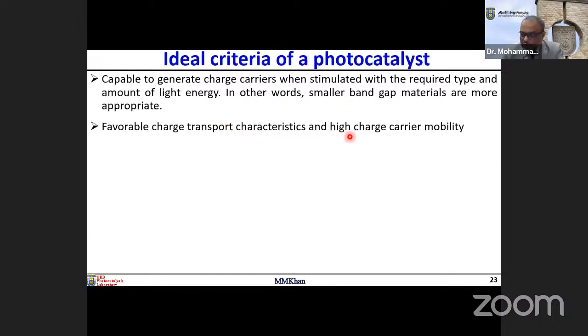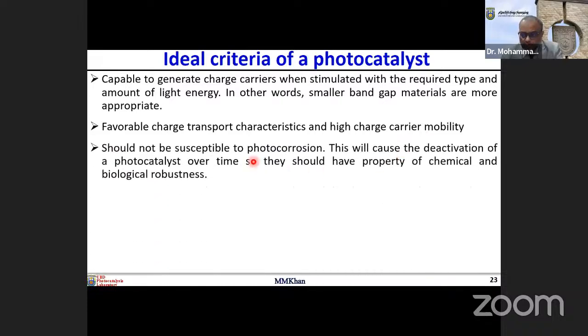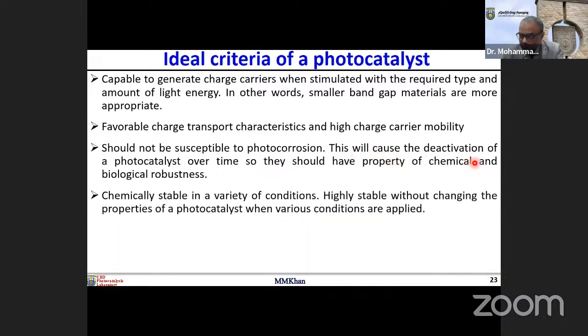Favorable charge transport characteristics and high charge carrier mobility are very, very important here. The material should have high charge carrier mobility so that you can reduce the recombination. It should also not be susceptible to photocorrosion. The material should not get photocorroded, because there are many materials, especially the chalcogenides, that get photocorroded. So the material should have anti-photocorrosion properties, because otherwise this will cause deactivation of the photocatalyst over time.